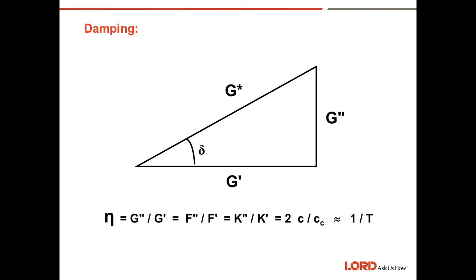How is damping measured? In order to design elastomeric springs with desired stiffnesses, we must know the static and dynamic stiffness characteristics of the elastomer. Elastic shear modulus G is the ratio of stress to strain — a measure of stiffness independent of geometry, similar to Young's modulus E, which is a tension modulus commonly used to describe metals. Shear static modulus G is measured at very slow rates of strain. When elastomers are sheared more quickly, there is a time lag or phase angle between the deflection and the resulting force.